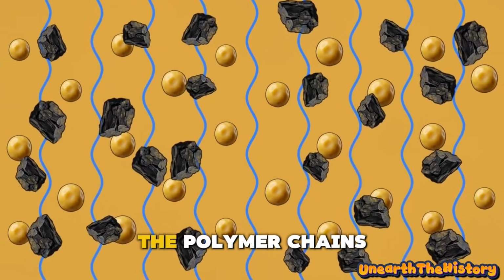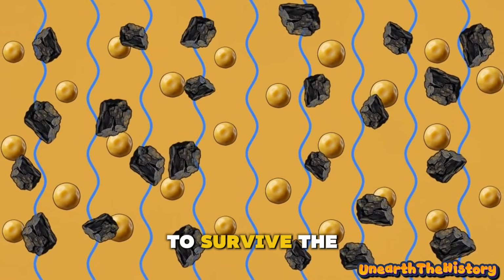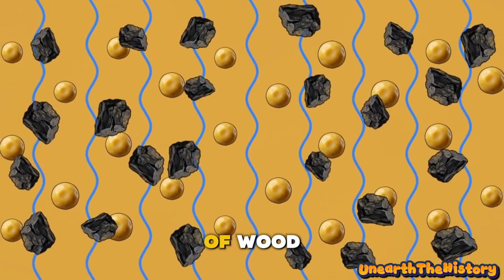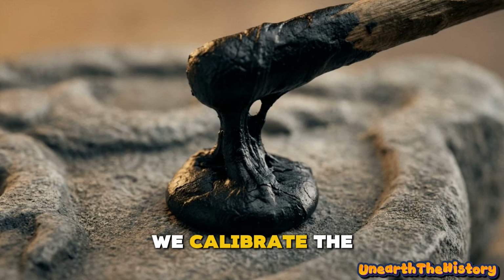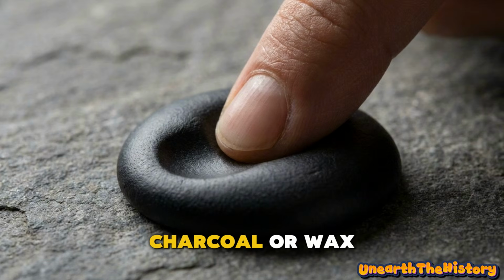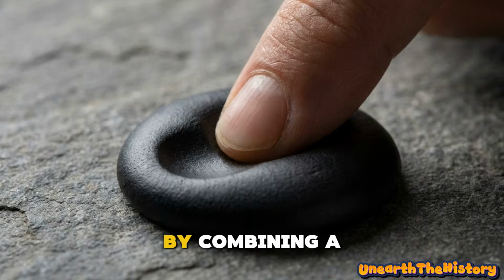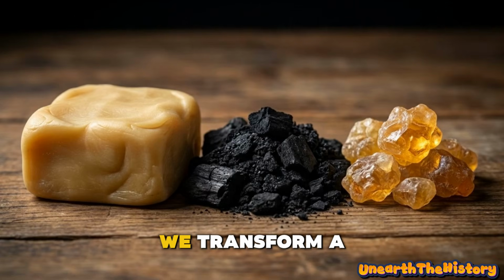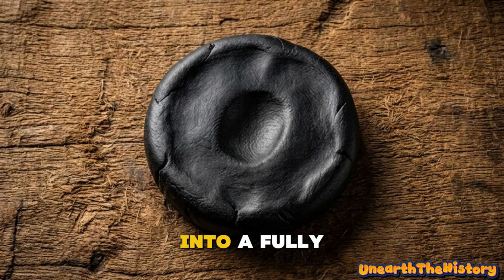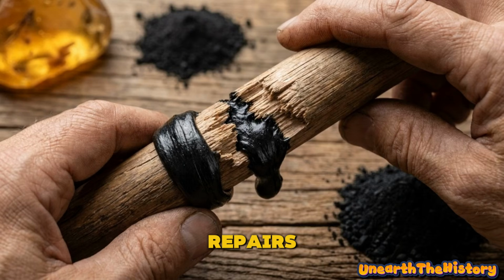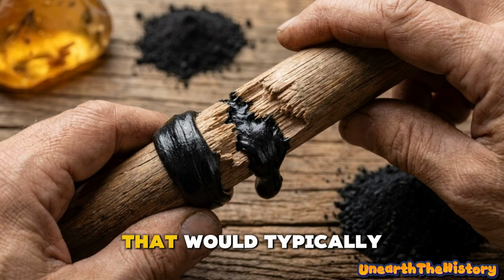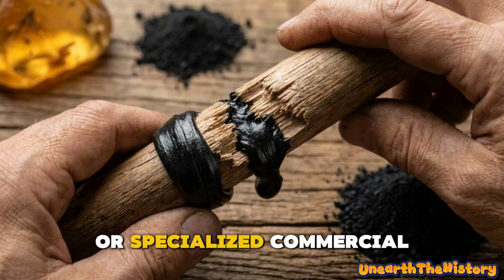The lipids separate the polymer chains, allowing the composite to survive the natural expansion and contraction of wood as humidity fluctuates. We calibrate the mixture by dripping the molten pitch onto a cold surface. We adjust the charcoal or wax ratios until the cooled material is firm but resistant to shattering. By combining a botanical polymer, a carbon matrix, and a lipid plasticizer, we transform a raw defense mechanism into a fully engineered biocomposite. This composite can perform high-strength repairs, such as fixing the broken tool handle that would typically require replacement or specialized commercial glue.